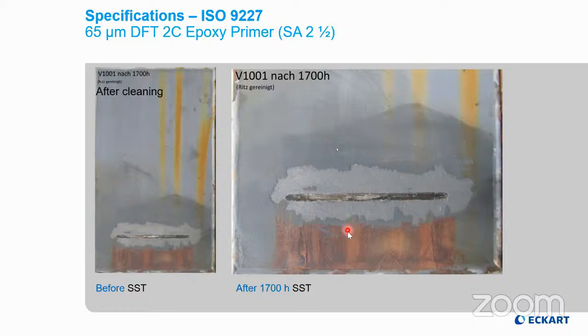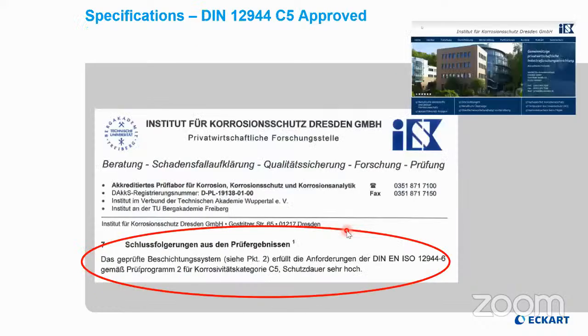You may now argue, okay, this is marketing material generated by Eckart in order to promote our zinc flake products. Therefore, we have approached in Germany, in the eastern German city of Dresden, a very well-reputed corrosion protective institute. And we have given them our paint and asked them to perform the corrosion protection test as per DIN 12944 for C5 class. And please believe me, it's a German certificate that with this paint, with this formulation, using our zinc flake at 12.5% PVC, the C5 corrosion protective category is fulfilled.